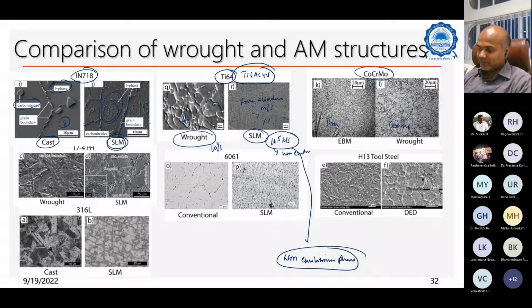This is called coarse grains. Okay. Sometimes you want to have creep properties. This is bad news. Creep is good, strength, this is good, this is bad. Okay. Look about this. This is 17-4 PH. 17-4 PH is a precipitation hardened stainless steel. And look again here also at the wrought product and cast product. You see a kind of difference in the microstructure. Okay. You see a lot of grains and small microstructural features which you don't see in the wrought process.